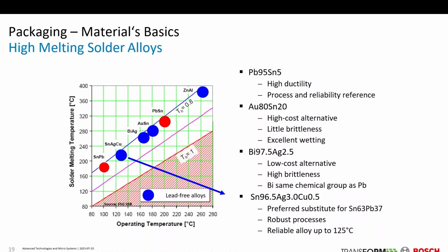For first level packaging, you can think about this bismuth alloy. You can think about a gold-containing alloy. The upper one is the standard for first level packaging. Unfortunately, the substitutes have a lot of disadvantages. This one is highly costly. This could be a low-cost alternative, but it has high brittleness. If you see this curve, with the operating temperature and the solder melting temperature, this is a slightly different sketch regarding the homologous temperature. You can find alternatives to this high lead-containing situation, but at the end of the day, it's quite hard to substitute it with another solder.